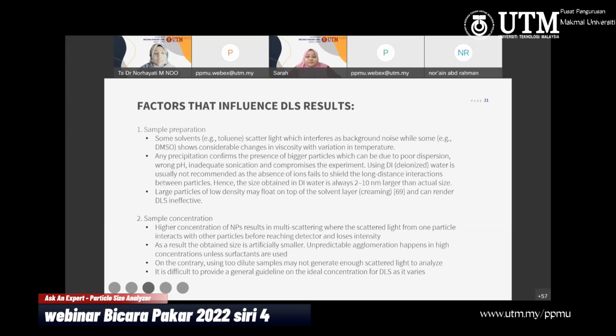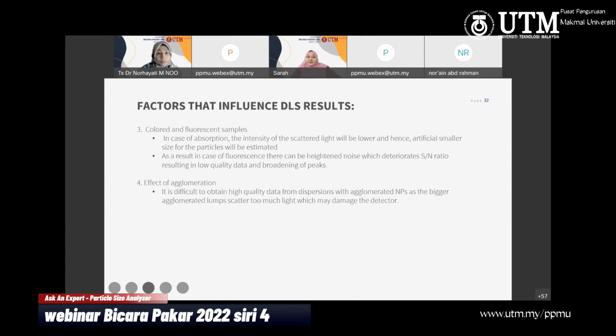results. And then sample concentrations. Like I mentioned, higher concentration might produce multiple scattering, which can give you the wrong results, and as a result the obtained size is artificially smaller and unpredictable agglomeration happens. And too dilute samples may not generate enough scattered light to analyze. So it's difficult to provide a general guideline on the ideal concentration for DLS, and it varies depending on your samples.